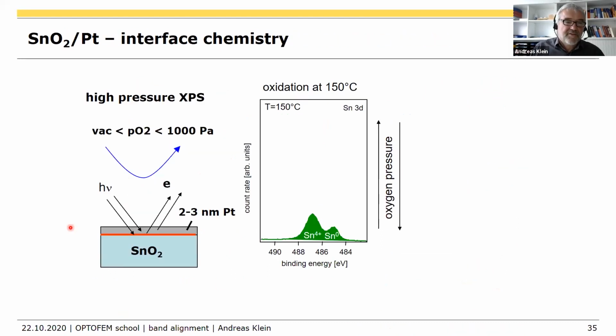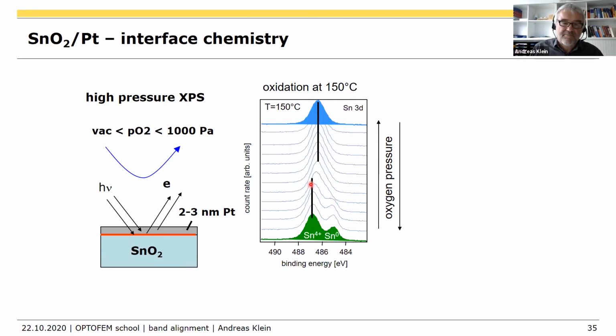We saw that also for tin dioxide. If you deposit platinum on tin dioxide, you also get tin 4+ and a metallic tin peak. What we now did in a near ambient pressure XPS system, we added some oxygen to the gas phase. And when we do that, you see that the metallic tin is disappearing. And you also see that the binding energy of the tin 4+ is changing. So the Schottky barrier height is changing. We can oxidize the interface and we change the barrier height.